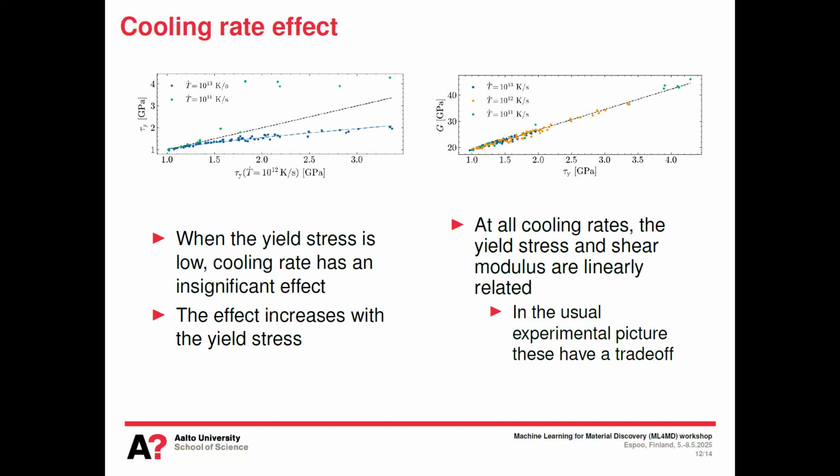And interestingly, we find that the shear modulus and the yield stress are linearly related at all cooling rates. In the usual experimental picture, you would have some trade-off between the modulus and the yield stress.